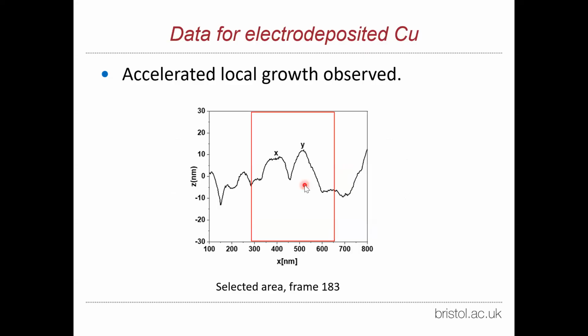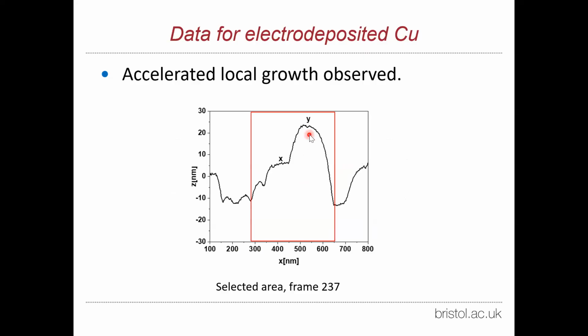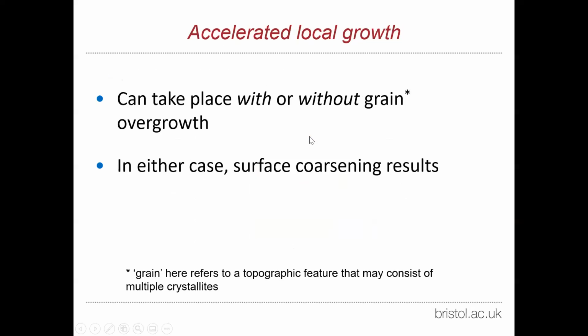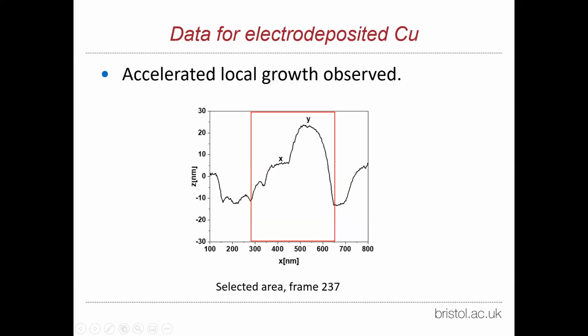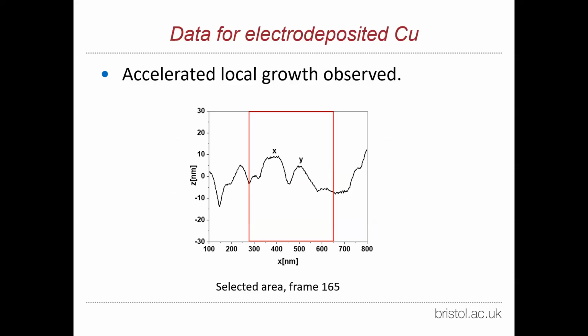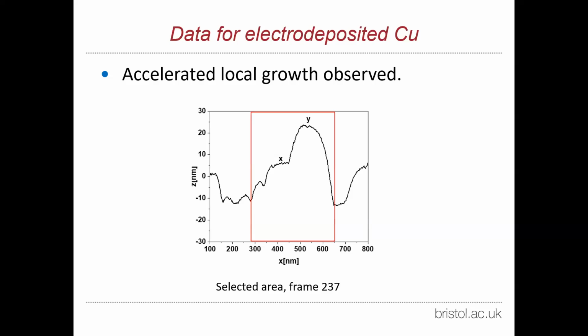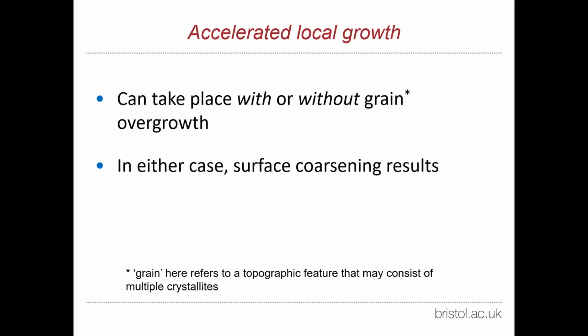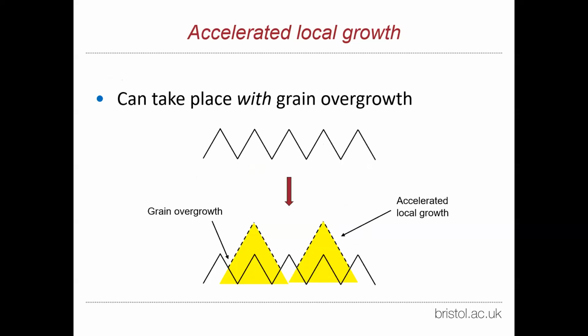Here you can see grain Y. Now it is about the same height as grain X, and now it is very much larger. So you can see that grain growth takes place in a very non-uniform way. Sometimes a small grain, Y here, can overtake rapidly its neighbor like that. And when you have got one grain growing faster than another, it could take place by overgrowth, as shown here. You can see that this grain grows outwards and it grows over its neighbor, and that will lead to a coarser structure.